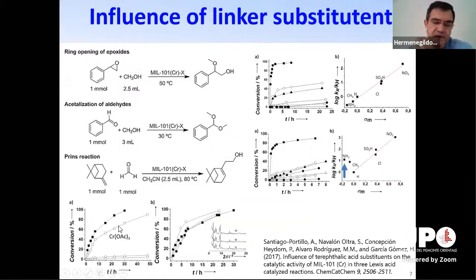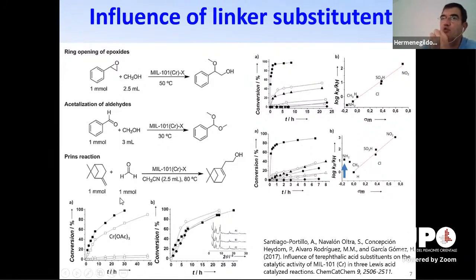Another comment on this slide is that we always check the performance of the MOF compared to an analogous homogeneous catalyst. And one of the most convenient examples is to use acetates. Acetates are analogs to the MOF, and they are soluble in many solvents. So for instance, if you compare here the activity of the chromium acetate with the MOF, what we have observed is that typically the activity of the MOF is always higher than the homogeneous catalyst. And this is because porosity and polarity of the internal voids increase the concentration of the reagents inside the pores, and because the reagents are more concentrated inside the pores, the initial reaction rate and also the rate of the reaction is higher.